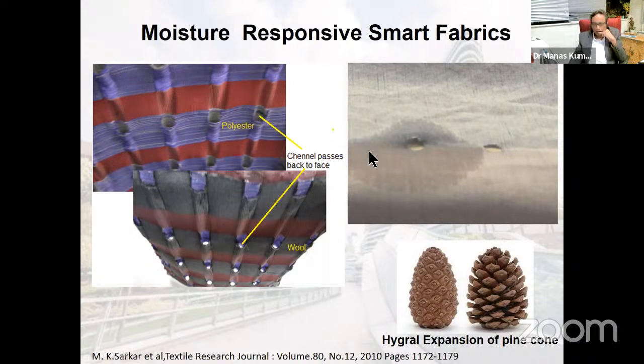So here, these portions we prepared using polyester, and this one we prepared using wool, and we cut it by laser. And we observed that when there is water, these portions swell up and the permeability increases. So here you can see the area of this one is less and the area of this one is more. Using this, we make a three-dimensional woven structure where the holes, you can see, are coming from the inner layer to the outer layer. One side of this is made of wool, and this is made of polyester. So whenever there is water, these holes become more circular and air can pass much better.